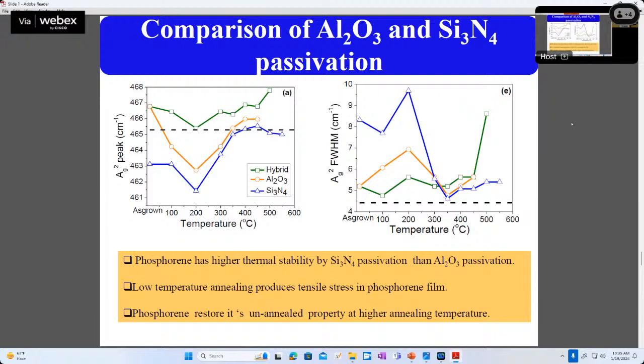Now we have compared both types of passivation to check which one is best. We found that the silicon nitride passivation gives high temperature stability in comparison to aluminum oxide passivation. Another thing we have seen is that if you do low temperature annealing of these materials, you will get tensile stress. But if you do high temperature annealing, it restores its properties. You can see here the dashed lines in these figures. This is the peak position for the bulk material. But when you passivate this material with some other material on top of it, the film is under stress. To release that stress, you need high temperature annealing in both cases.